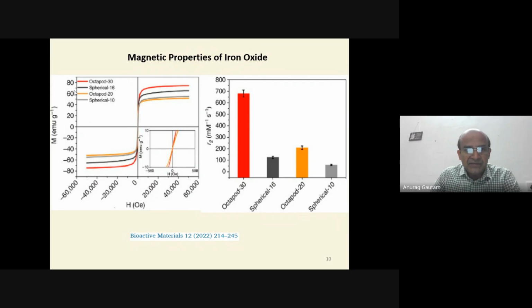So for different purposes, if you take a smaller particle, there is variation in the magnetization, because the number of contributing ions is lower in the smaller particle. If your particle is 30 nanometer, there are more ions, so the magnetization is higher. If they are 16 nanometer, the number of ions involved in making the particle is less, so they have less magnetization, so certainly the relaxivity will be less. Similarly for 10 nanometer, it is small, but it also depends on shape and size. So it is possible that a certain very small size, maybe 10 nanometer, can have high magnetization. That will also have higher relaxivity.